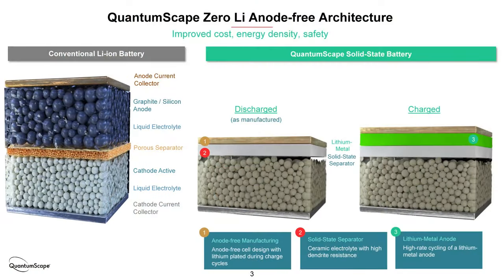So in our case, there is no host material, and the lithium that cycles back and forth inside the cell from cathode to anode and back simply plates itself on top of our solid state separator as a layer of pure metallic lithium, because there's no host material like carbon or silicon for it to intercalate or diffuse into. And that's really what gives you all the benefits of this approach.